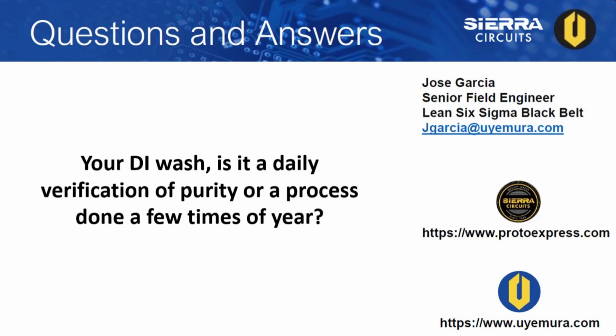Typically, we will start at about 3 gallons per minute, just to make sure that we have enough turnover and limit the conductivity buildup in the rinses.